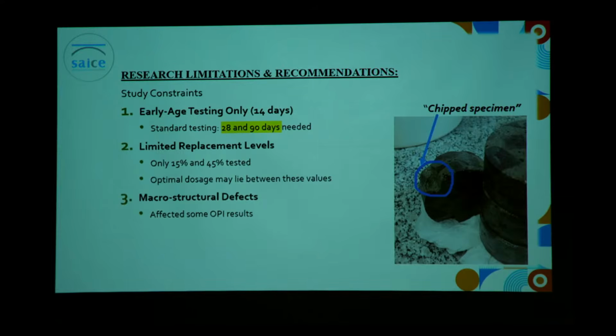However, due to those unforeseen circumstances, I had to make something out of my research, so I decided to reshuffle my objectives and really look at the development stage, at that early stage of our concrete mixtures. And that limitation itself influenced the number of replacement levels I had, 15% and 45%. Then I couldn't really find the optimal dosage of our replacement level because it could be lying in between that 15 and 45%. However, we were deeming our result as promising as we had seen some of the benefits.